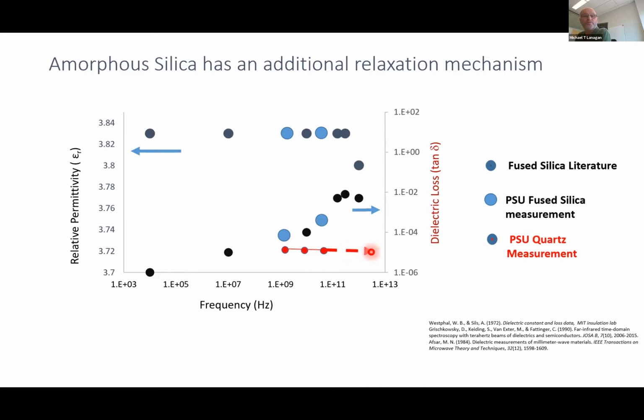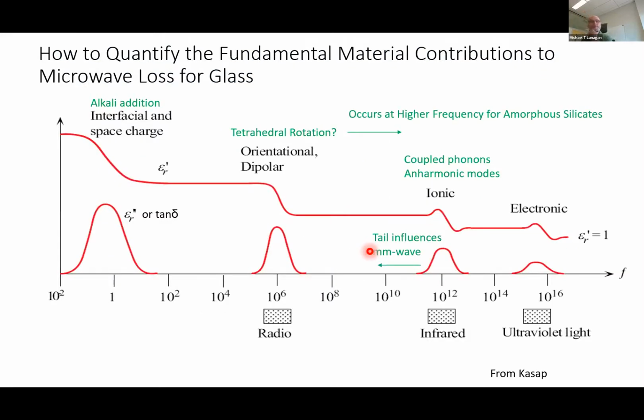So that quartz sample, we can see, has a very low dielectric loss and no peak here. So there is a fundamental difference, even though the chemistry is exactly the same, between the crystalline and amorphous structures. So if we look at this, we think basically what's happening is this tetrahedral rotation. It's actually maybe more of a dipolar response in glass, but we also have some of these influence of these coupled modes and anharmonic modes in the IR range that really pushes down here as well.